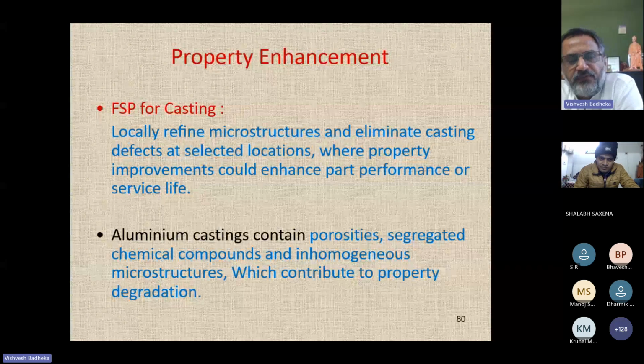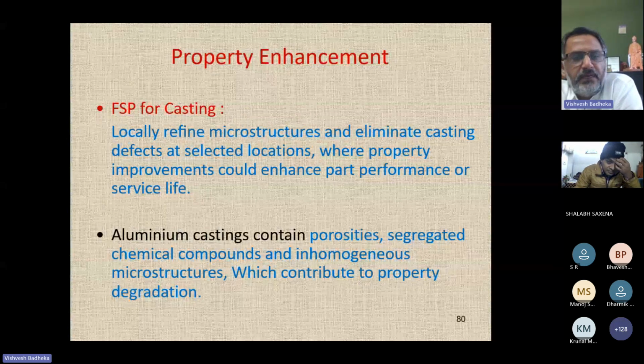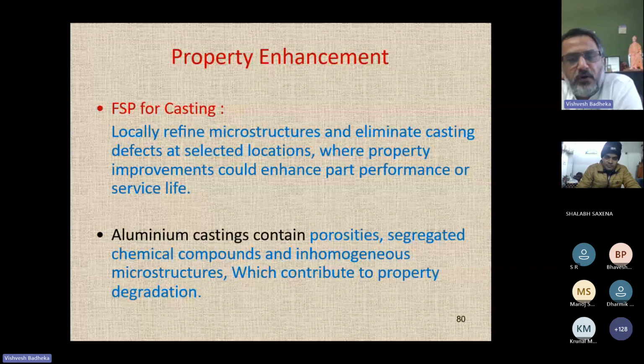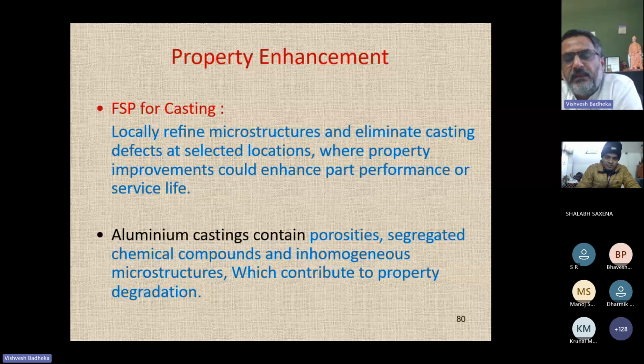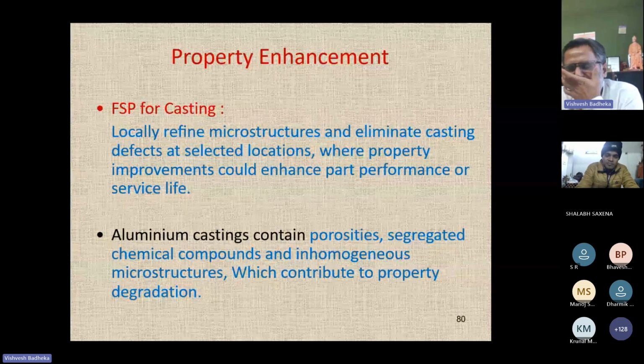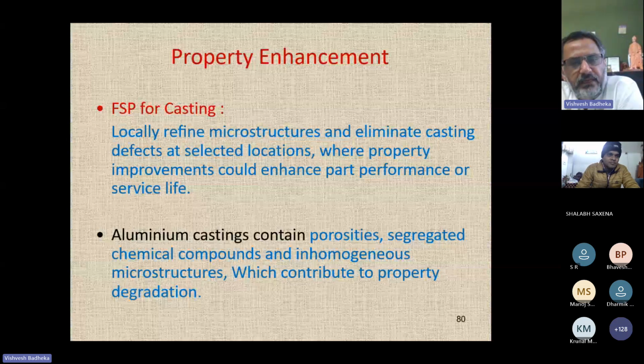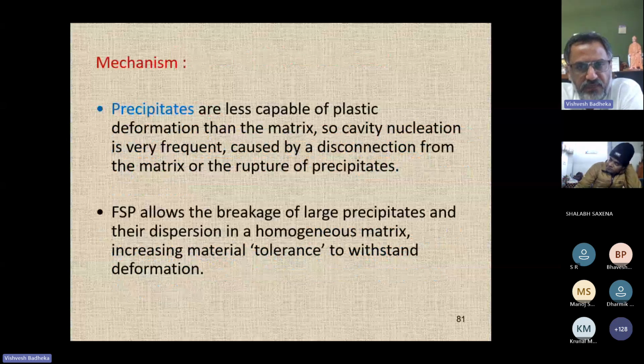Now, with the help of FSP, you can locally refine the microstructure and eliminate the casting defects at selected locations where you want a property improvement, which could enhance the part performance or the service life. So these are the benefits you will get. People have tried FSP as a tool in castings, superplasticity, and even for surface composite manufacturing.